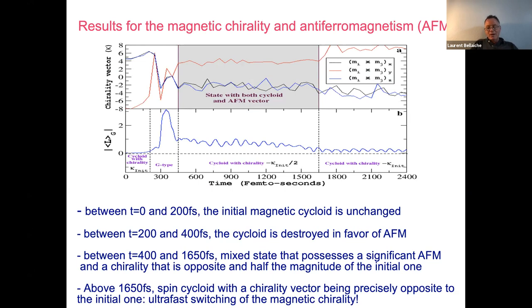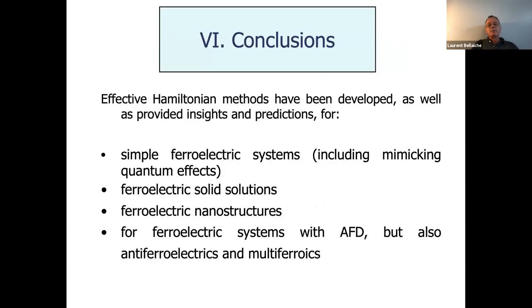Between 400 and 1,650 femtoseconds, suddenly you have an opposite chirality, but half of the initial one. And finally, above some time, the spin cycloid has a chirality vector that is exactly opposite of the initial one, which means what you have done is an ultra-fast switching of magnetic chirality. You went from a right-handed magnetic cycloid to a left-handed magnetic cycloid by applying an electric field. It's a very nice magneto-electric effect, and this can be done these days with effective Hamiltonian simulations.